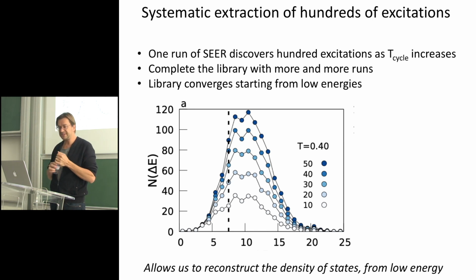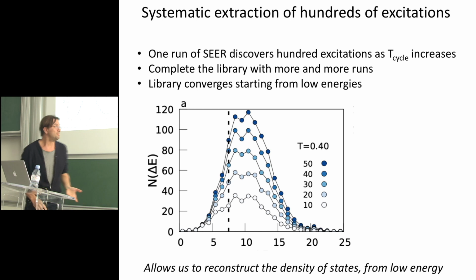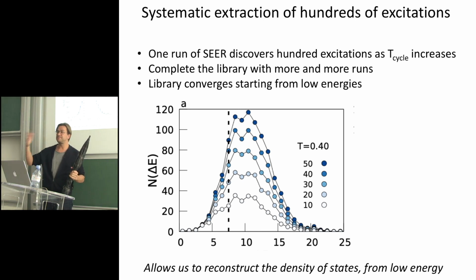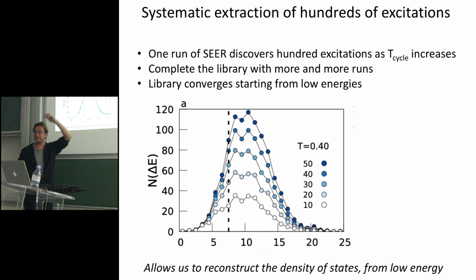What we do to seek to be systematic, to have most of them, is that we don't just do one run, we do 10, 20, 50 runs. And every time we discover a new excitation, we put them in the library. Then you can measure a density of states, the number of excitations at some energy level. What you find is that at low energy, it converges. So it seems that you have access to all the excitations you could find in a range of energy. At large energy, no, we certainly have not converged, and those curves we should not trust. So at least for some hundreds of excitations, we can start to reconstruct an estimate of the density of states.